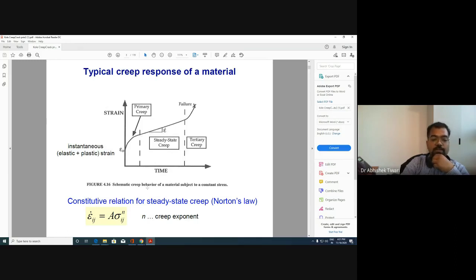So there, usually, it follows a power law and it can be stress dependent. If it is stress dependent, it follows this kind of equation: the strain rate is equal to some constant times stress to the power creep exponent. And this kind of law is called Norton's law.